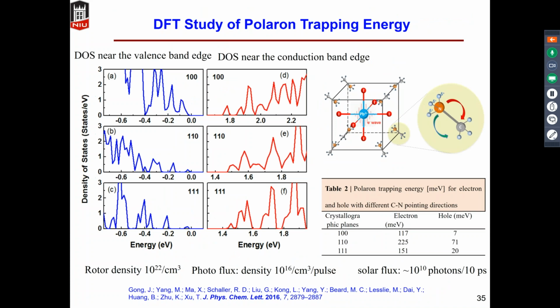Our theoretical collaborators also provided some DFT calculations, and they found that when the rotors align in different directions with respect to the crystal faces, the polaron trapping energy changes significantly. For example, when the rotors are aligned along the 100 plane, the electron trapping energy is much different from when you change the orientation of the rotors to the 110 direction. So this indicates that there is some interaction between these rotors and the photo-induced charges.